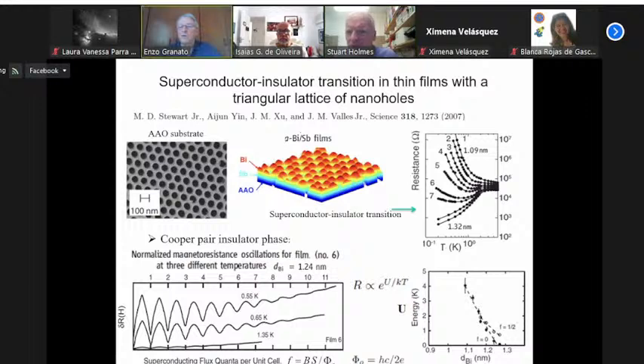And then you get the oscillation. Yeah. So it's basically what comes in the exponent of the superconducting order parameter. There is a contribution for the vector potential. Every time that it is around 2 pi, it repeats. Now, this explains the oscillation for integer field. I mean, this main oscillation here.